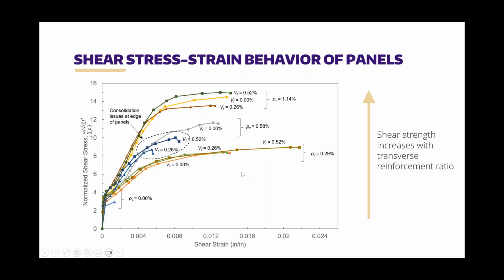What you can see from this plot, there's a couple of things to notice. It looks like there might be some influence of the fiber volume in terms of the strength. So this is kind of hot off the presses, so we're still working through the statistics on all of this, but you can see that at least for these high reinforcement ratio tests, there is potentially some increase in shear strength using that higher volume fraction of fibers. When you get down to the lowest reinforcement ratio, you do see an improvement in the strength and deformability. And in the middle here, you can see that there's some trends that maybe don't quite make sense in terms of the fact that the panel without any fibers looks like it did quite a bit better.